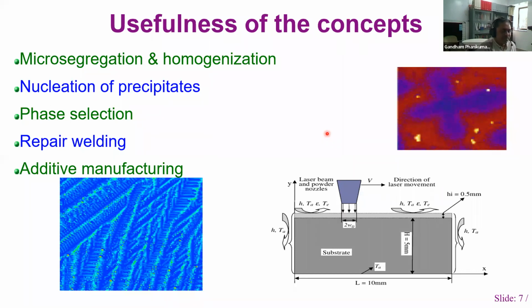And we should also understand the precipitate nucleation, because we don't want to nucleate unwanted phases. For example, Laves phase in Inconel alloys, nickel-based superalloys, is a headache, and you would not like to have Laves phases when you build a component out of nickel-based superalloy powder. Sometimes phase selection also will play a role.